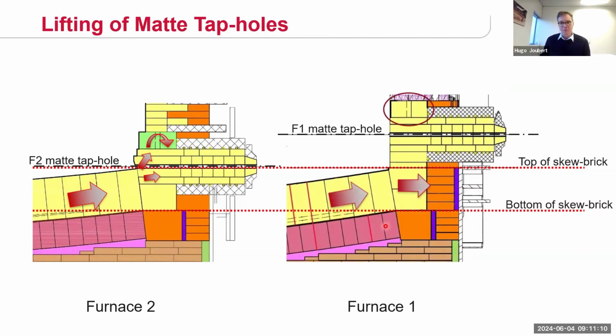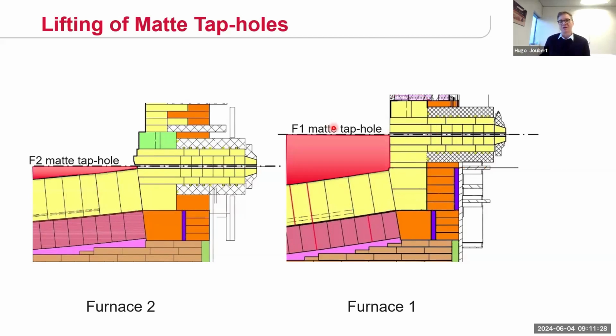And as you can imagine, one of the big advantages, if you do have thermal expansion of the hearth now, is that your skew bricks are more likely to slide underneath, if I call it like that, underneath your matte tap-hole, and you have less distortion taking place in the tap hole itself. Another big advantage is that you end up with a much deeper matte bath that's maintained underneath the tap hole. The advantage of this is that it acts almost like a thermal flywheel, and it helps to reduce the thermal cycling in the hearth bricks as well as the critical skew brick area.